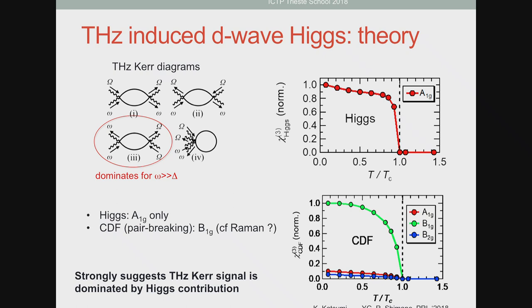While the pair breaking peak, or the charge density fluctuation contribution, if you want, will be predominantly in the B1G channel. And this is actually what is observed in Raman measurements in cuprates. In Raman measurements in cuprates, the dominant contribution is in the B1G channel, the one that is probing the maximum of the superconducting gap. But in this kind of measurement, this is different. It's dominated by the A1G channel. So the tentative interpretation is that the A1G contribution is essentially coming from the d-wave Higgs contribution. And the B1G component likely comes from this pair-breaking contribution that dominates the Raman spectrum.